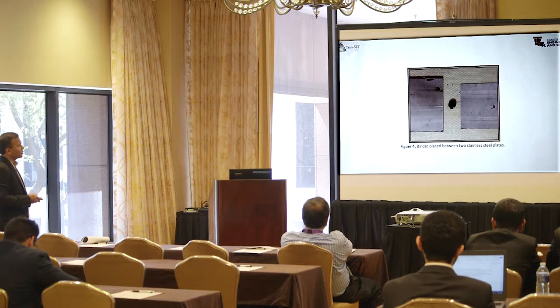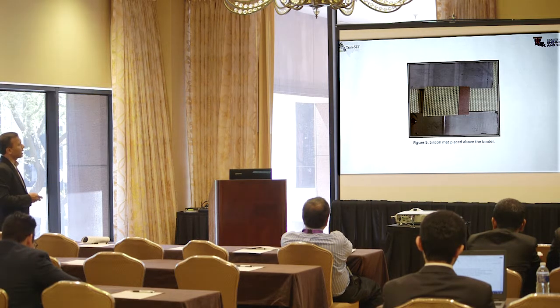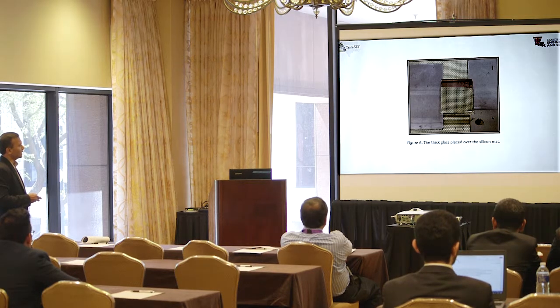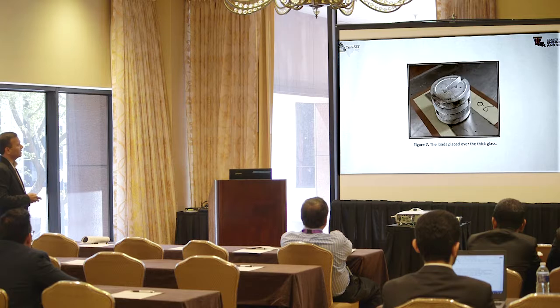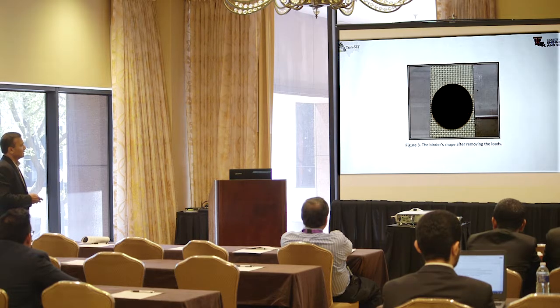So that's why we use this one, and then we put again a silicone mat on top of this one. Then we put a glass plate. You can see there is a glass plate here, and then we put load. This is 20 pounds of load on top of that. And then we kept it for a long time. Earlier we used 12 hours. We changed that later on.